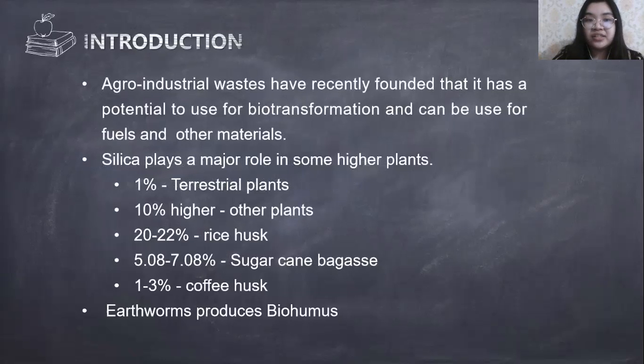For our introduction, agro-industrial waste has recently been found to have potential for biotransformation and can be used for fuels and for other materials. And here, it contains amorphous silica that can be transformed into crystalline nanoparticles. Silica has a major role in some higher plants. The silica absorbs 1% of the dry matter of some of the terrestrial plants, while other plants have 10% and higher. Research even stated that rice husk constitutes 20 to 22% of its total production, 5.08 to 7.08% for sugarcane bagasse, and 1 to 3% for coffee husk.